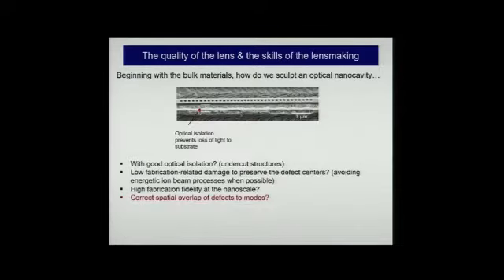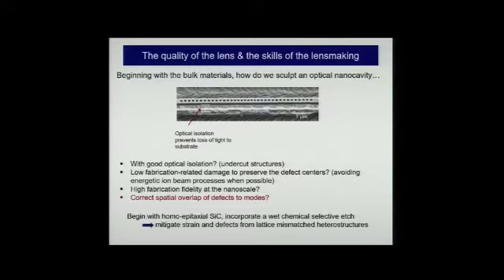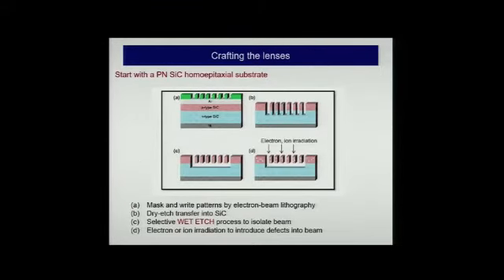So again, this is far more beautiful, but this is our nanobridge. Just very roughly, what we do is begin with the bulk. We begin with homoepitaxial silicon carbide. We're very fortunate that we can get commercial material where we ask for a PN junction, and they can grow it for us. And we incorporate a chemical selective etch, and this is just a summary of the process. This is something that we've worked on in excruciating detail, Alex in particular. But I will go through it just very briefly.